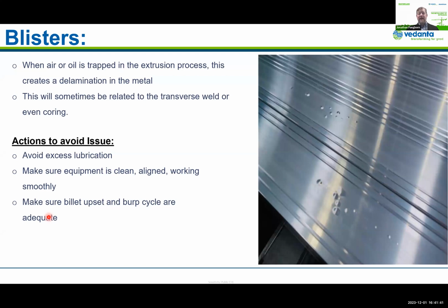And I would say if you have a shear, that's probably what you're going to stick with, but make sure it's well maintained, that the shear blocks are properly cutting, and you're doing the least deformation you can get with a shear. With regards to lubrication, the action is to avoid excess lubrication. Sometimes I think our operators feel like if a little lubrication is good, more is better, and that is not the case. Just the proper amount. Again, it's not necessarily a recipe parameter, but it is a factor that we need to control in our process, and having a clear understanding of what lubrication we're going to use for what part of the process, and making sure that it's done in a controlled manner.